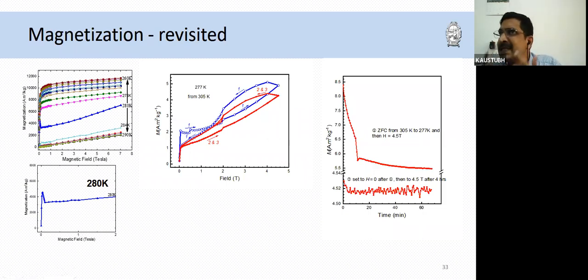So what we thought is there must be some spin dynamics. So we did a time-dependent experiment. We followed the same protocol, cooled it in zero field from above its Curie temperature to the desired temperature, and we applied a strong field of 4.5 Tesla. Then we saw how the magnetization behaves as a function of time. Initially, the magnetization decreased very sharply. Then there was some kind of a discontinuity and it started decreasing very slowly, indicating that there are two types of relaxation times, one which is a short relaxation and one which is a fairly long relaxation. We continued the measurement for about 60 minutes, or about 1 hour. At the end of 1 hour, we switched off the magnetic field.